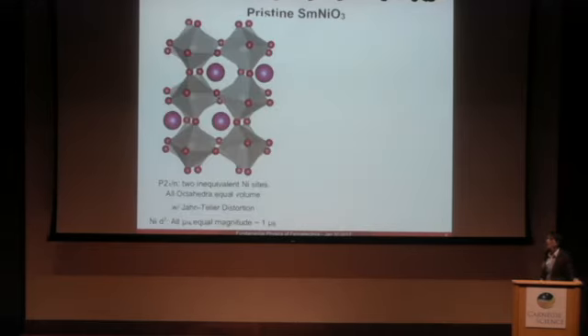So, as I said, the pristine samarium nickelate at room temperature and low temperature has a P21/N symmetry. This means that we have 2 inequivalent nickel sites in our 4 nickel unit cell. In this case, even though we have 2 inequivalent nickel sites, all the octahedral volumes are equivalent, and there is a Jahn-Teller distortion. Because the nickel is in a d7 configuration, we end up with magnetic moments that are all equal and about 1 Bohr magneton.